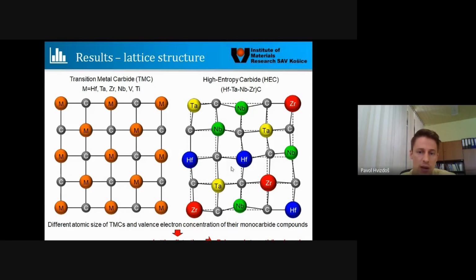This lattice distortion is due to the fact that we have different transition metal elements with different atomic size and different valence electron concentration. So this distorts the lattice a little bit. This is an exaggeration of that lattice distortion, but I wanted to emphasize that this is real, and this can also be measured, and it has already been confirmed by different techniques that lattice distortion exists. This lattice distortion should cause strength or hardness enhancement, which makes it difficult for dislocations to move forward.